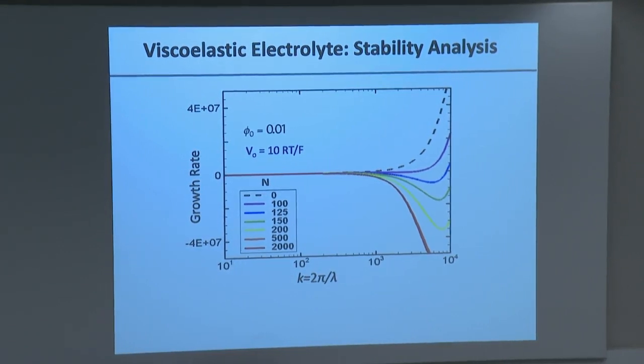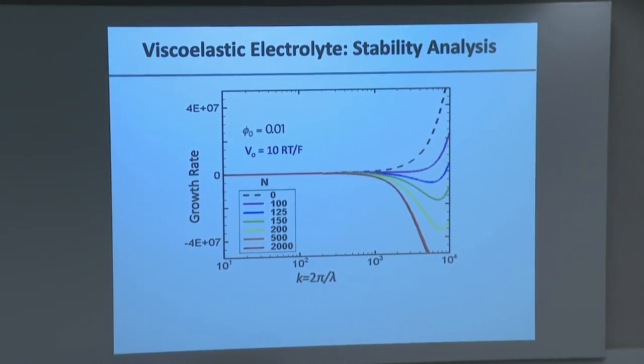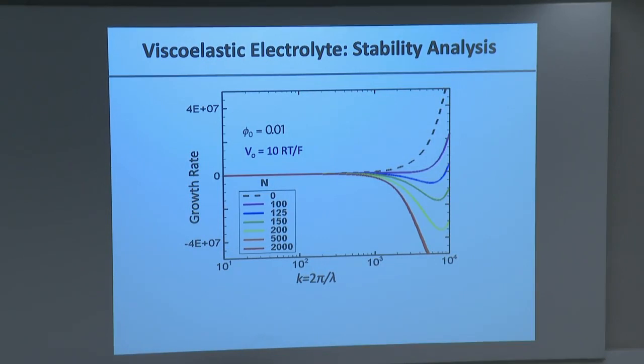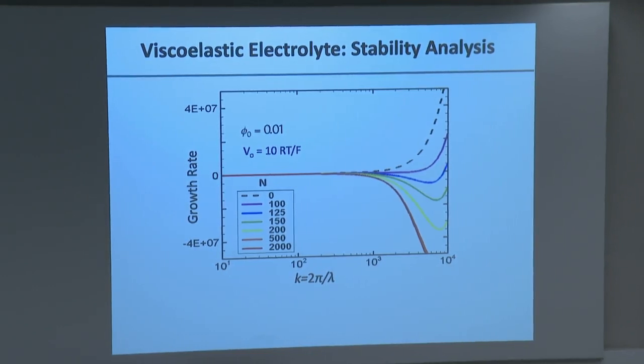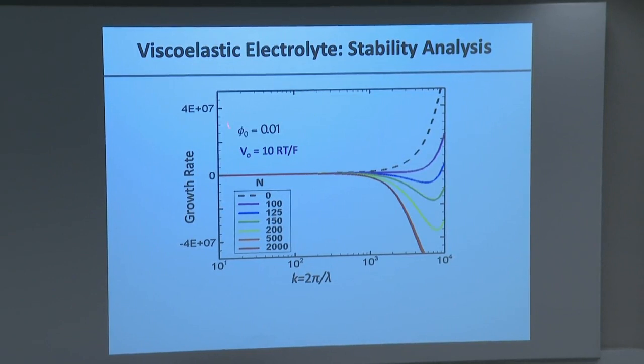So we are well into this zone of bad stuff, all right? And the question we were asking is, is the growth rate negative or positive or zero? Obviously, if it's positive, it means the bump once formed will grow, and the thing is unstable, we will get dendrites. If it's negative or zero, it means the bumps once formed will not grow, and that is a good thing. And so what we decided to do is for a fixed polymer concentration to vary the molecular weight of the polymer and monitor the growth rate for different sizes of the initial bumps.